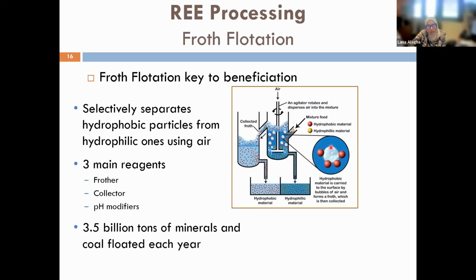And then the optimum size for the mineral in flotation operation depends on the ore itself or the mineral that you want to float. Usually, for example, if you want to float sulfide minerals, the size is between 90 to 75 micron. If you want to float phosphates, it is between 125 to 90 micron. It depends on the nature of the material that you want to float.